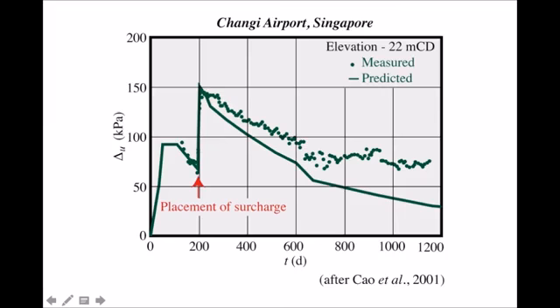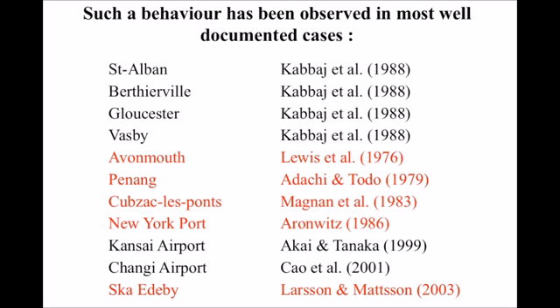But at the same time, they were not able to have such good agreement in terms of pore pressures. And in all cases, the measured pore pressure was larger than the predicted one, which is, again, in the logic of the strain rate model, with the in situ compression curve below the laboratory one. Now, this has been observed in other cases in UK, in the States, in France, and in Sweden.